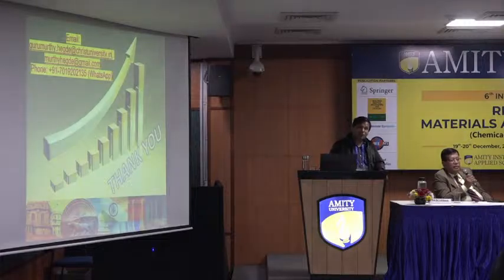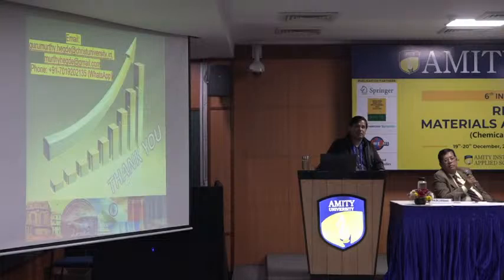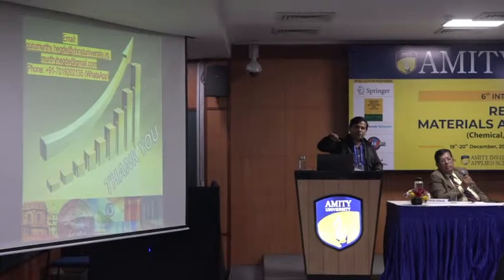Yeah, exactly. That's why you have to do the TGA, because thermogravimetric analysis means we are heating in an inert atmosphere and checking how the weight loss takes place. You should know at which temperature complete weight loss takes place. Otherwise, also without TGA, you can synthesize the nanoparticle, but you have to do lots of experiments, because you don't know whether 500 degrees, 600 degrees, or 700. But once you do the TGA, you know exactly where the drop takes place, where 90% of the weight loss takes place. After 500, where complete weight loss takes place, it's a safe region, so you can directly go to 1000 degrees or 800 degrees. Otherwise, you have to do the experiment for 200, 300, 400. It saves your time. It's not gradual, right? It's not gradual. Good. That's a very important finding.